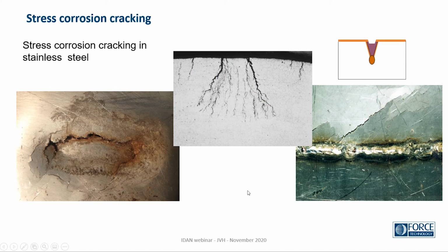The stresses we talked about could give stress corrosion cracking, which is a corrosion process combined with stresses which form cracks, which both are branched and which form very quickly. In the laboratory, we can make stress corrosion cracks grow like 1 millimeter per day, per 24 hours. But fortunately, in the actual world, it's not going that fast. But it is definitely a risk if we get into an area with sufficient salts and sufficient heat and sufficient stresses, then you have this kind of problems.